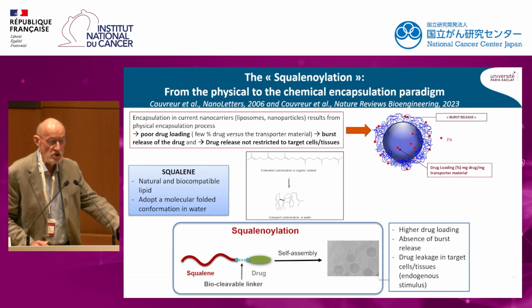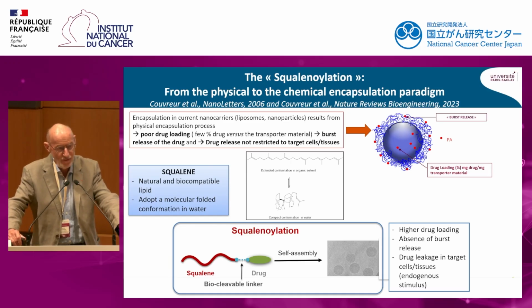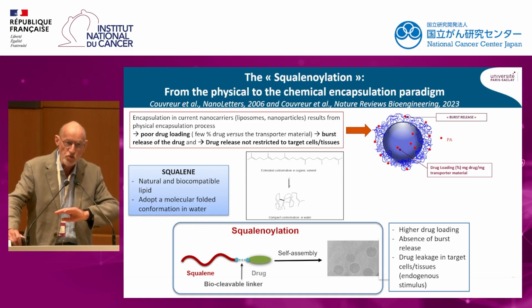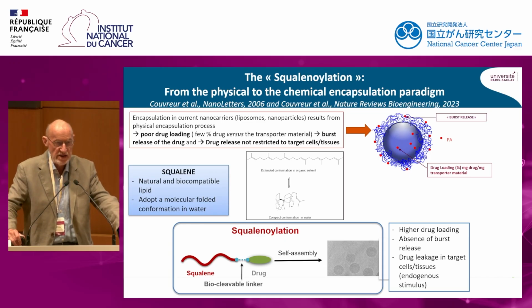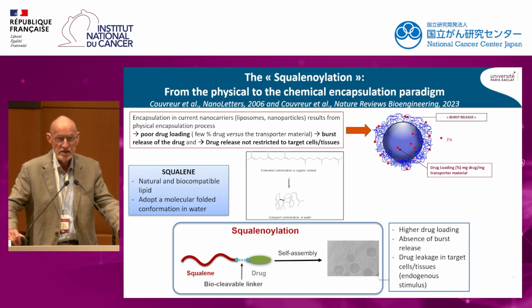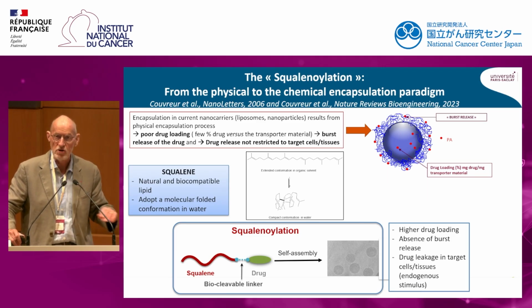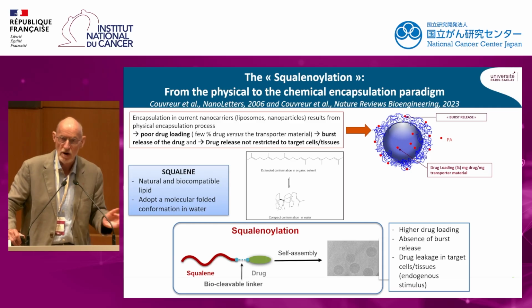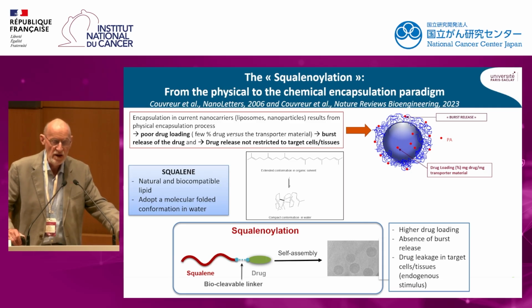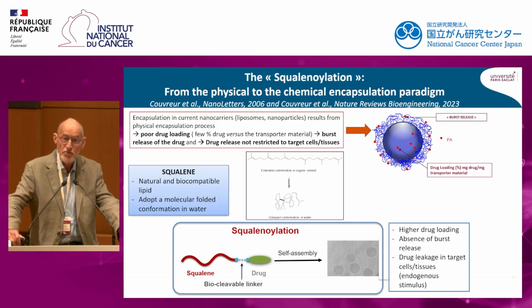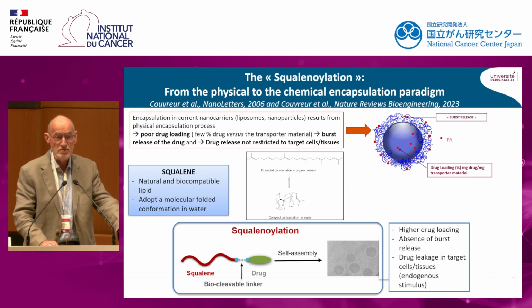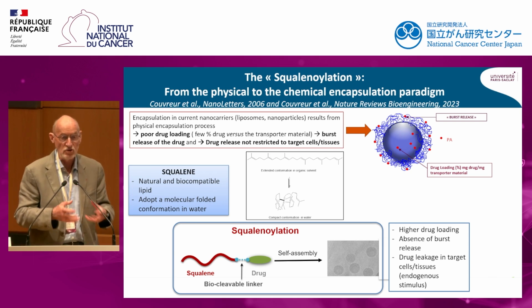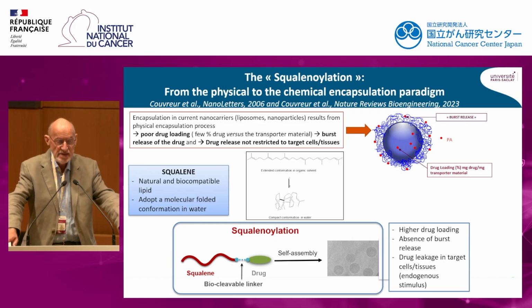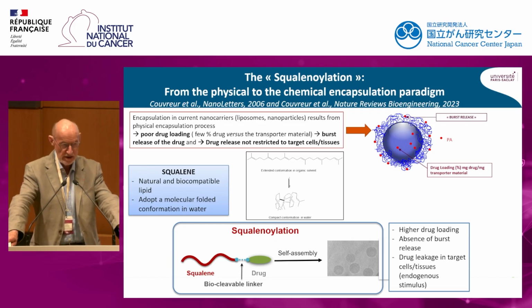But during all this experience, we observed finally, and this is true for all the encapsulation methodologies, that in fact the encapsulation of drugs in the current nanocarriers, including liposomes, nanoparticles, polymer micelles, etc., always results from physical encapsulation processes. This means adsorption, entrapment, encapsulation. And this has three very important limitations. The first one is a poor drug loading.